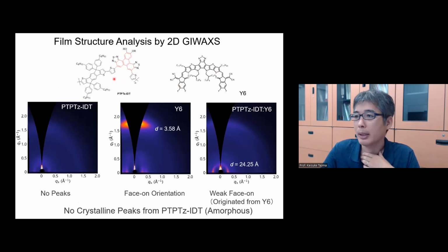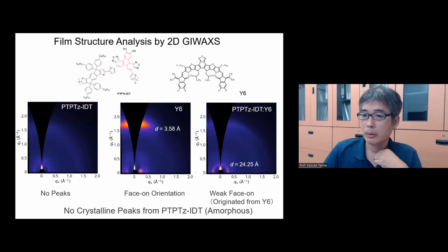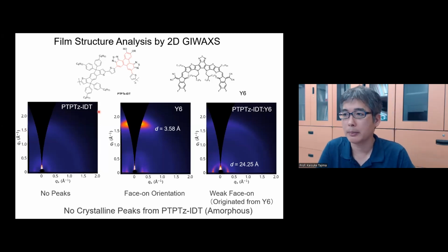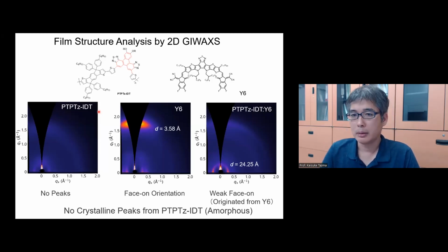Unfortunately, this polymer doesn't have a high crystallinity. It's almost amorphous, no peaks. And the Y6 has a strong tendency to have a face-on orientation, which is good for the solar cell. And in the mixed film, sure, we don't see any peak from the polymer. So it's actually not very useful to use the X-ray diffraction pattern for this kind of mostly amorphous film to know the molecular orientation in thin film.